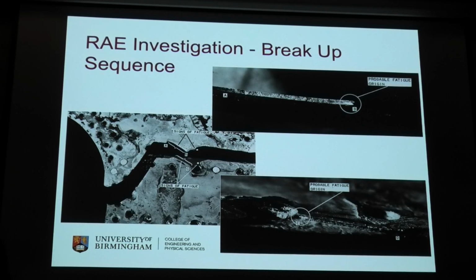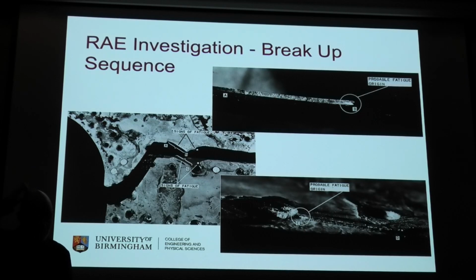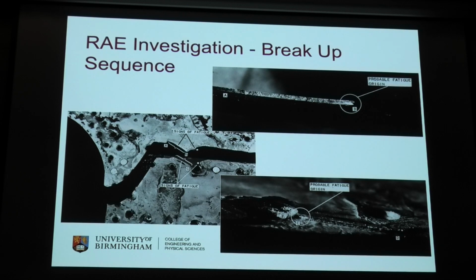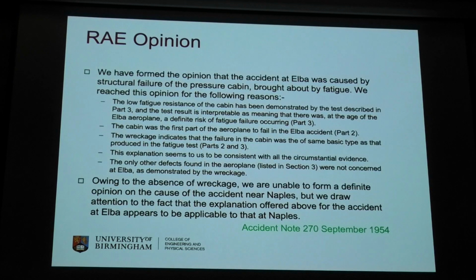Now, it could be argued that should have been picked up on service, but this was underneath a doubler plate that was around the window. So to actually find it on a very young aircraft, you'd have had to strip all the paint off, take off the doubler plate from being on top, and then go in, and that was never going to happen, not at that age of aircraft. So this was highly unlikely to be picked up. That's from the actual report, those photos.